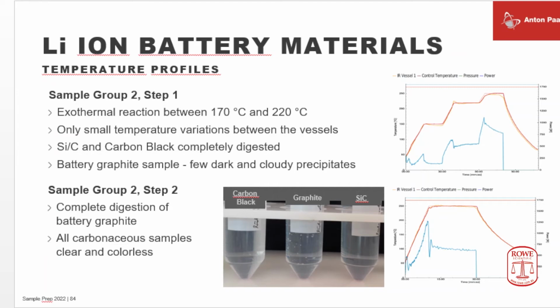And this is typically the time when you prove if the digest was complete. Shake the tube, hold it against the light and see, are there any particles in there? Dark particles, undestroyed residual carbon. Light particles, maybe undestroyed silicates. No particles, you've done a good job.